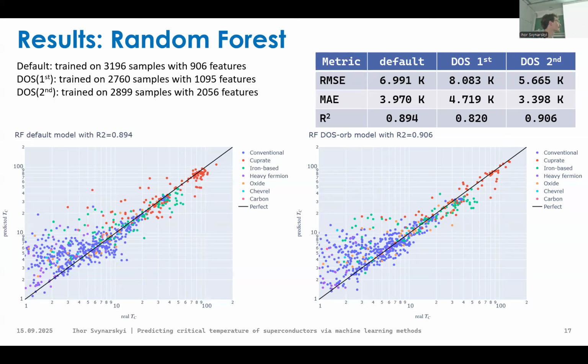It varies. Let's say for the conventional superconductors with low temperature, you can see that blue dots are basically aligned below the 10 kelvins temperature, and for them, root mean square error was around 5 kelvins, let's say, and for the cuprates shown in red, it was like 7-8 degrees. But you could also see that their temperature is an order of magnitude bigger, like 10 times. So for them, having an error of like 7 kelvins is more or less okay. And that's why I'm using log scale here, because it's more representative. So in other words, for high Tc the method is reasonable, but for low Tc, less so.